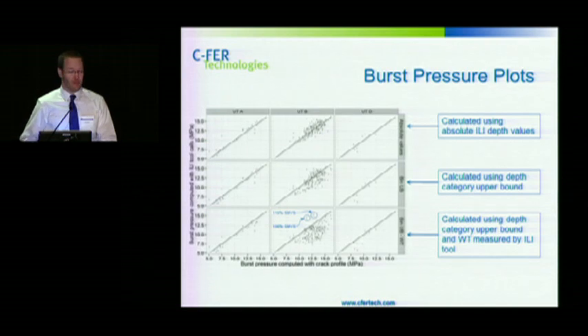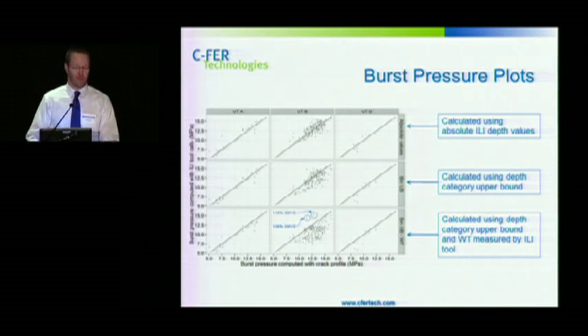This is a burst pressure unity plot. This is one of the ways that we looked at assessing the sizing accuracy of the tool. There's a bunch of plots on here. I'm going to focus on the middle one at the bottom. So what we've done here is we've calculated burst pressure using the ILI data, and then we've calculated the burst pressure again using the field profile data. There's roughly 200 data points on this chart.